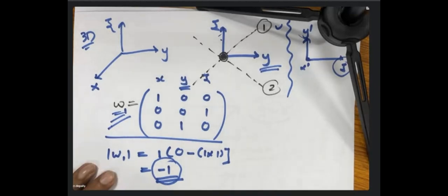So yes, it is an improper transformation, which gives weightage to our answer that we found the reflection, and due to the reflection we are getting this particular symmetry transformation matrix. And since it represents the symmetry transformation matrix for the reflection, no matter whether the reflection is along the x-axis or y-axis or z-axis, whatever the plane, x, z plane, y, z plane, the determinant will be minus 1 only. And that's what we are getting.